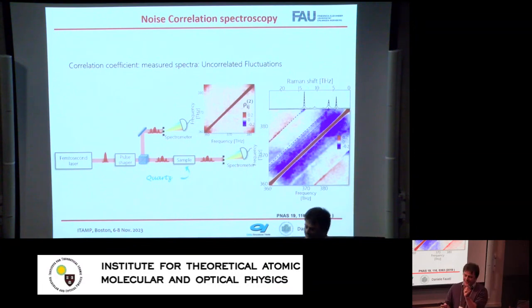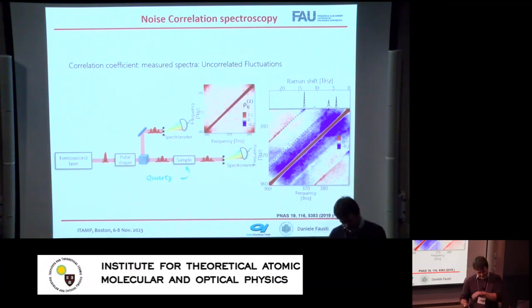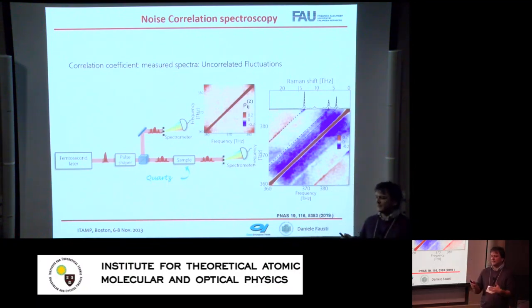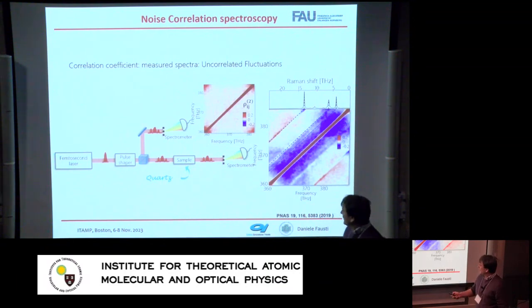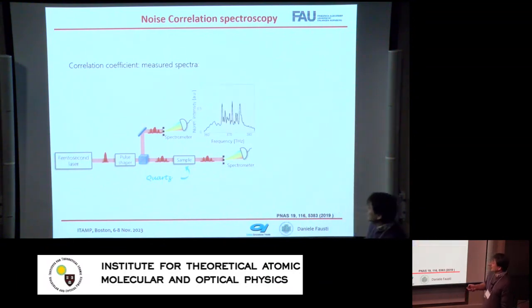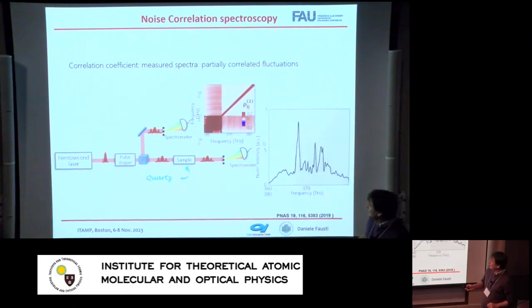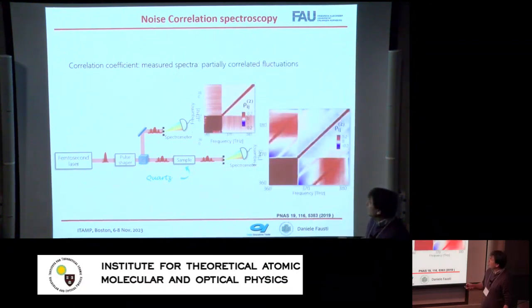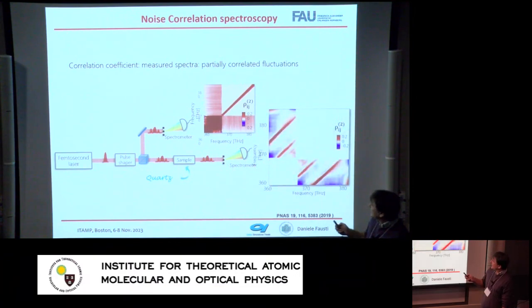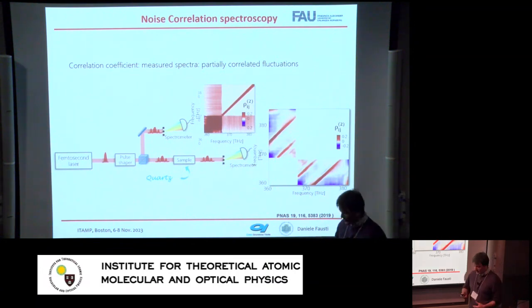Instead here, as I said, you cheat around the indetermination in the sense that your frequency resolution is given by the width of the noise, while your time resolution is given by the inverse of the width of the pulse. So that's a little bit like femtosecond Raman spectroscopy. This can be done in many forms. I just go fast here because I want to go to the cavity, but essentially you can also partly shape your light pulse, and you can measure even weakly scattering phonons, and you measure them with relatively high frequency and time resolution.